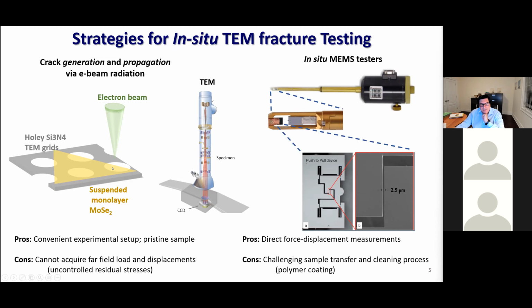The beam can be used to induce a crack and also propagate a crack, and under certain conditions you can visualize the atomic structures. So it's a convenient experimental setup, but it has a major drawback, which is that in this experiment we are not measuring the loads and displacements like in a more controlled experiment. We just have some sort of uncontrolled loading, but still we have a lot of information about the atomic structures at crack tips, and I will show you that.